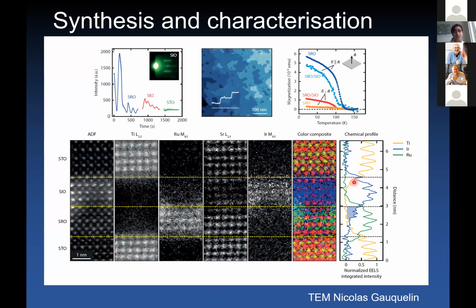And so we synthesized this type of heterostructure. Again, the excellent work of Dirk Groenendahl and Thierry Fantil made this very difficult synthesis possible. And we also benefited from a lot of TEM characterization by Nicolas Gauquelin. But the insight from TEM is that the interfaces are very sharp, except the top interface, strontium ruthenate, strontium iridate, that has an intermixing over 1 or 2 units of iridium and ruthenium.